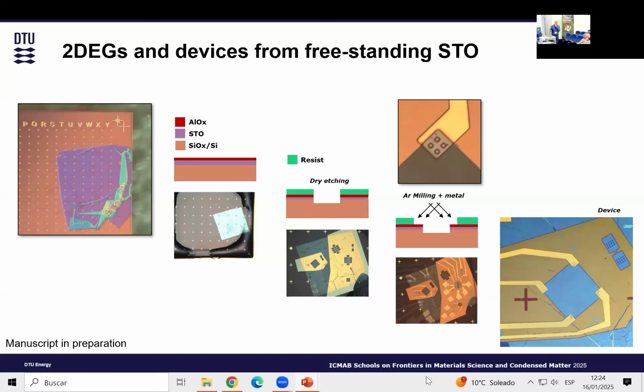So these are some of the work that we did to start with. We took STO and put it on silicon. Then we wanted to create a 2DEG in the material. First of all we tried to use LAO on top of it. We didn't succeed. We went back and said, okay, if we put a very thin layer of aluminum and then oxidize it, which is basically what people already did, we maybe could get the 2DEG in the material. So we did it. So we started to do all the procedure. And I will stop here. We had a problem.